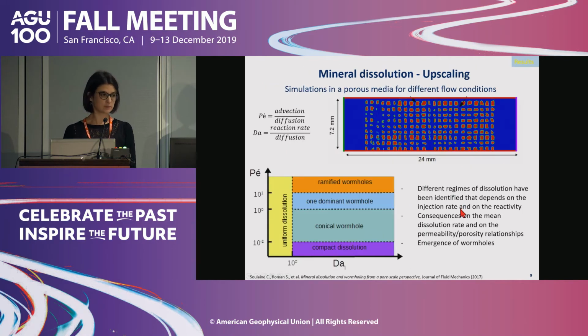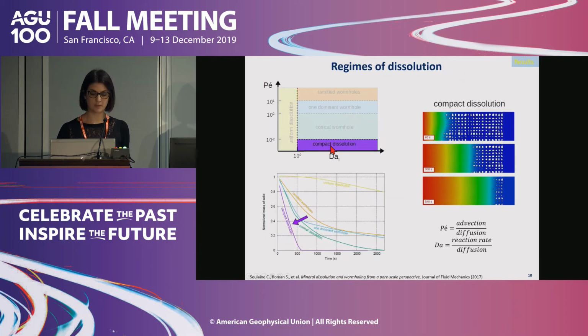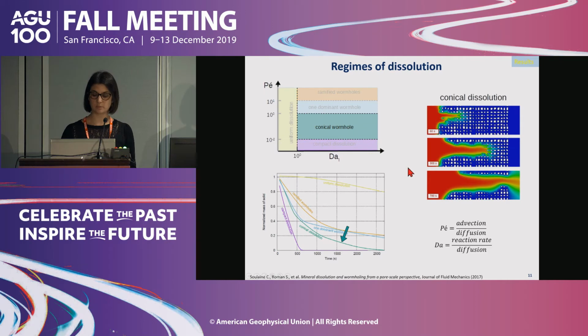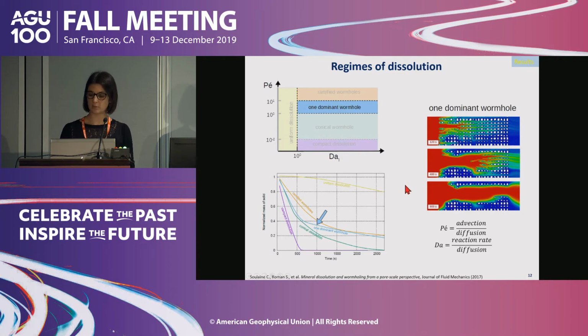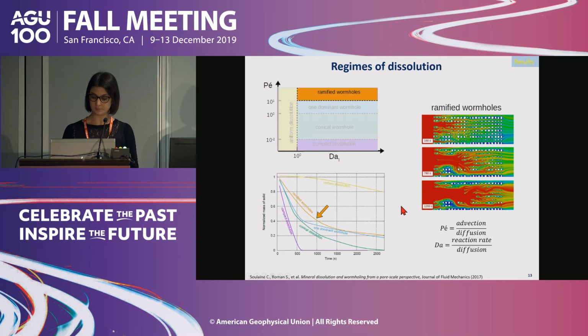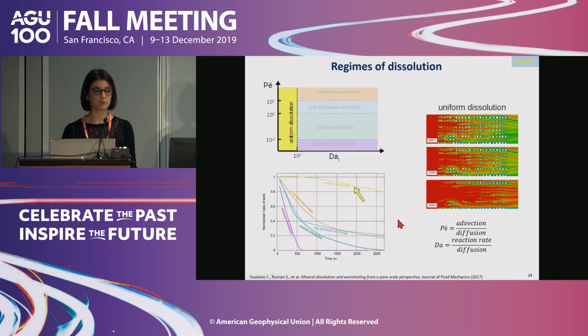So now that the code was validated, we were able to perform simulations for more complex cases, where we have an array of calcite crystals. For different injection rates and different reactivity of the media, we were able to show that we have different dissolution regimes that depend on the Peclet number and on the Damköhler number. For example, at very low Peclet number, when diffusion is dominant over advection, we have a compact dissolution, with a very uniform front. Then as we increase the Peclet number, we have one preferential path for the dissolution. And as we increase it again, we have the emergence of wormholes and ramified wormholes. And for low Damköhler number, we have a uniform dissolution.